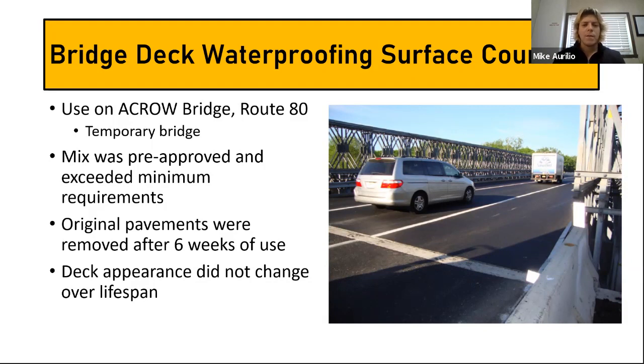The reason they developed this mix though was because the original pavement they were using was being torn out every 6 weeks. Again, according to the report, the appearance of the pavement didn't change over its lifespan, and they considered it to have very, very good performance over about 1.5 years.